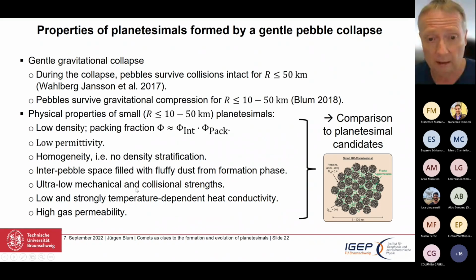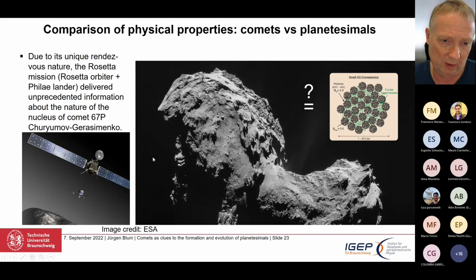The mechanical and collisional strength of the pebble piles that make up these planetesimals are super low. I'll show you numbers about that in a few minutes. The heat conductivity, as shown before, will be extremely small at low temperatures and will be strongly temperature dependent at high temperatures, which might be a measurable unit. And the gas permeability might also be relatively high due to the large void spaces between the pebbles, which might be an interesting thing for cometary activity.